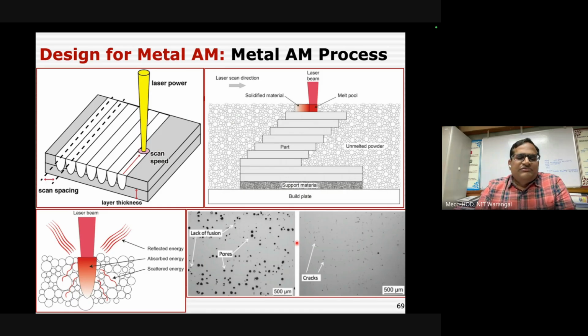And then metal, yes, of course, is a bit more challenging than the polymer. Why? Because you have high melting temperatures, so we try to understand some parameters like scan space, layer thickness, scan speed, and your energy absorbed, energy reflected, energy scattered. None of the lasers is more than 70% efficient, it may be 20%, 30% efficient. Nowadays you may have fiber lasers, where again the efficiency may be less. But anyway, you have lack of fusion, pores, cracks. Then we need to understand how to minimize this.